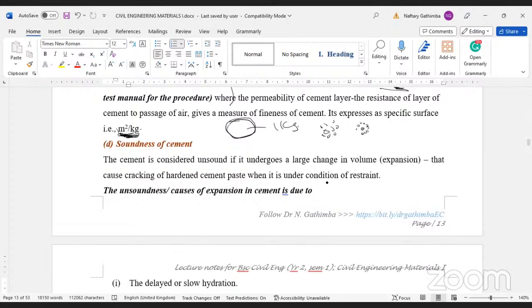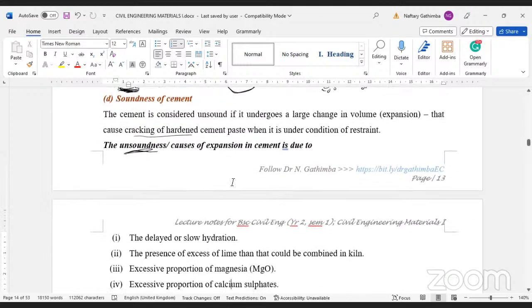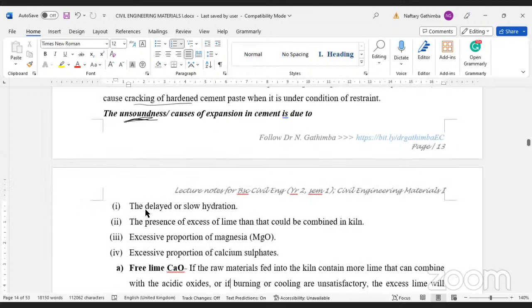Now, cement, you see, when it comes into contact with water, heat is generated. And that heat may cause expansion of either your cement paste or concrete. Of course, we give allowances, but if that expansion is too much, we say that your cement is unsound. So that's another property, because if they expand too much, it may cause cracking of hardened cement paste. So what will cause unsoundness of cement? One of the properties that will cause unsoundness of cement is what we call delayed or slowed hydration. You see, let's say we have particles, and then they are covered by hydration product, the hydrated silicate, so that we have unhydrated particles inside.